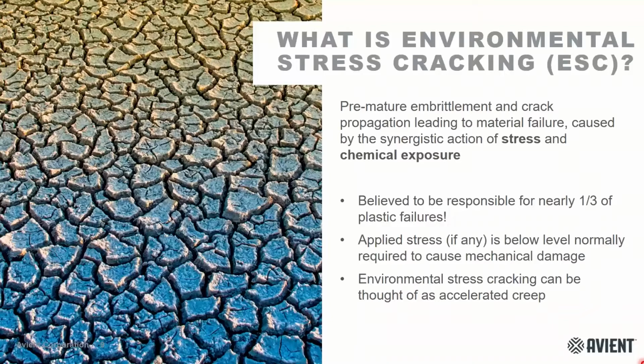And so what we're talking about is, if you're looking at a stress-strain curve for a material, you would say, this material I know it's going to yield at 3%, for example. The critical strain that's required for stress cracking can often be a fraction of that percentage. Another thing to note is that environmental stress cracking can be thought of as an accelerated creep.